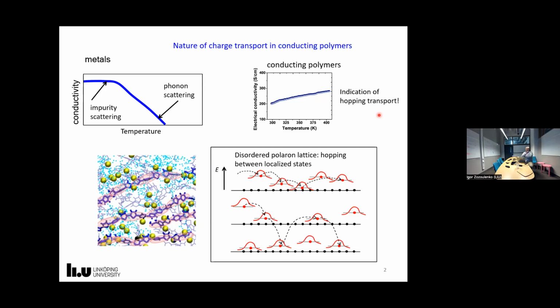Okay, let's now take a little bit closer look at the origin of hopping transport. Again, I already showed this picture previously. We basically have these polaronic states, and they are energetically and also spatially disordered states, because each polaronic state feels a very different environment from counter ions, maybe from solvents, from chains. So therefore, the energy difference would be very different for each of these possible polaronic states. This type of diagram represents very well what you have in conducting polymers. So you have different states, and basically you have this hopping character of transport between different states.